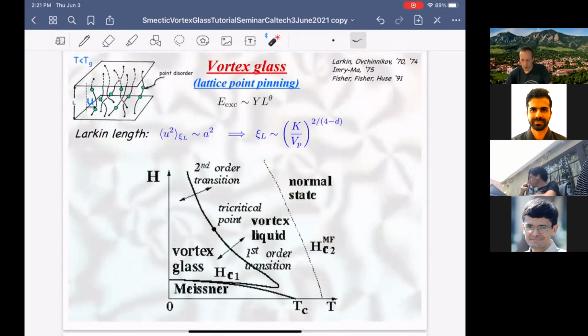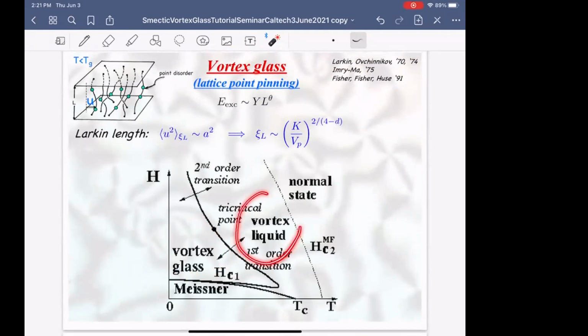Okay, thanks. Suffice it to say, already here, that part of the reason, at least a practical reason of interest in glass, is that this elastic medium is now pinned, goes into a glass state, and the key observation by Fisher and Huse in the early 90s is that this is really a superconducting state, in contrast to a vortex liquid. It really has an Edwards-Anderson-like order parameter, made up of a superconducting order parameter.